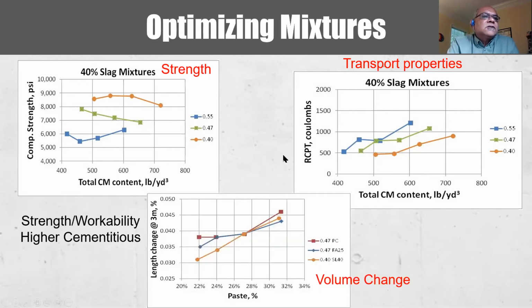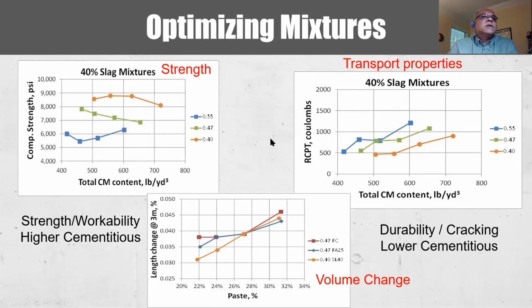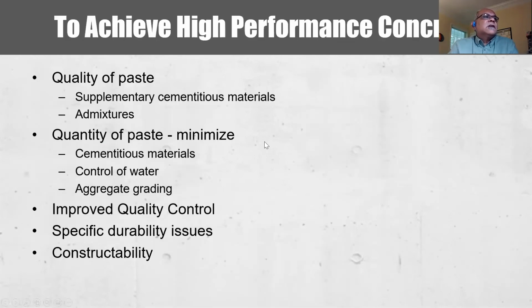And the same thing works with volume change. As your paste volume in your concrete mixtures increases, your shrinkage increases, therefore your potential for cracking, either due to drying shrinkage or due to thermal or temperature issues, also increases. So in this sense, performance-based requirements, when applicable, actually help optimize mixtures and also improve their sustainability. So durability and cracking tend to lower your cement content.